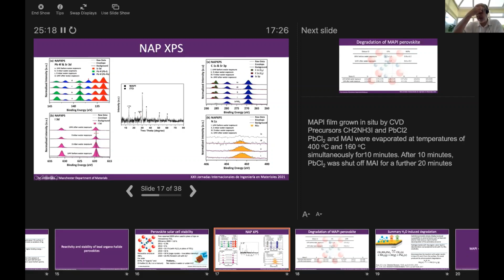It doesn't matter how we prepare these perovskite films, whether it's in vacuum by vacuum deposition, in aerosol-assisted chemical vapor deposition, or by spin coating and using anti-solvents, which is the kind of preferred method, we always see this metallic lead when we measure these things with XPS. What we find in this case, though, as we increase the water vapor pressure in the ambient pressure cell to 3 millibar and 6 millibar, is that we start to see this lead peak decrease in intensity, and the metallic lead peak starts to increase in intensity.